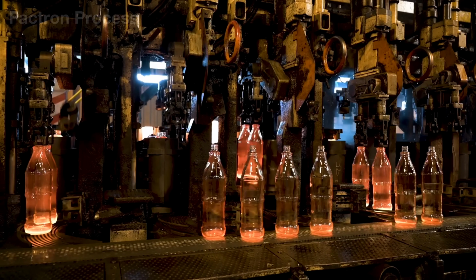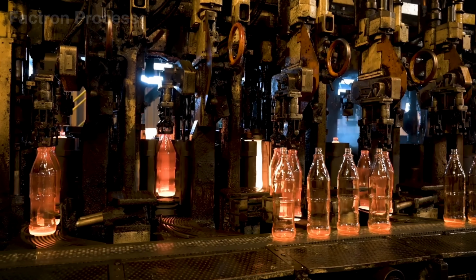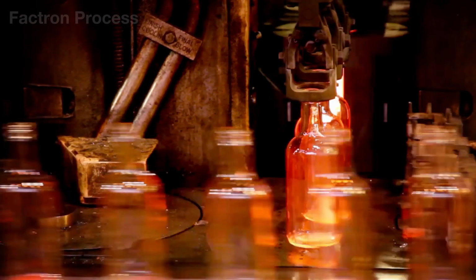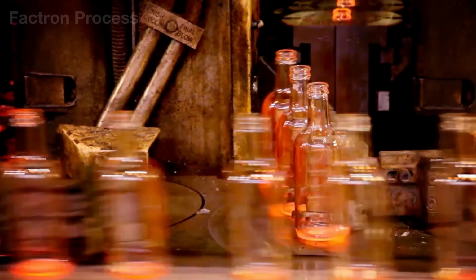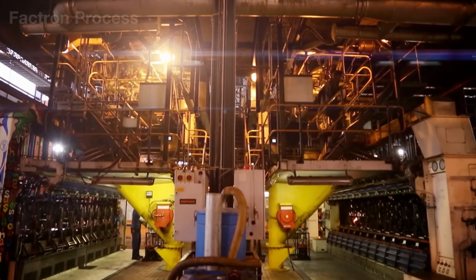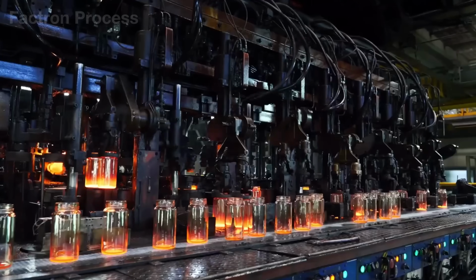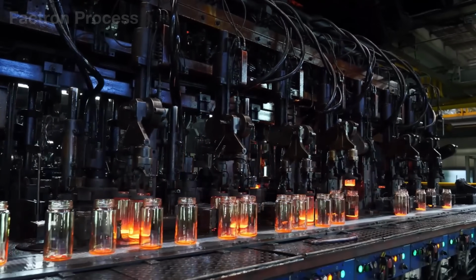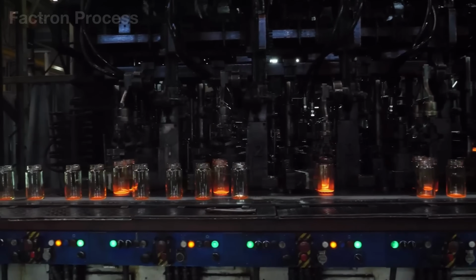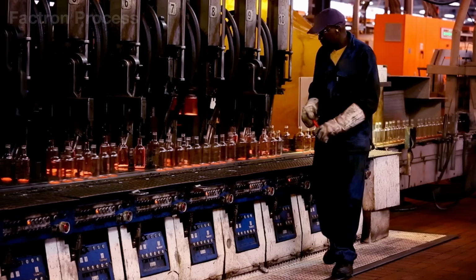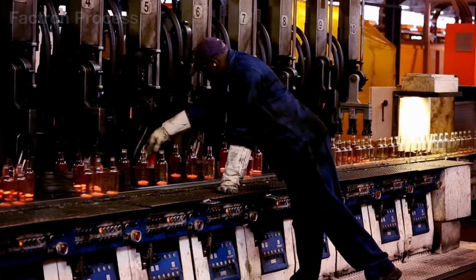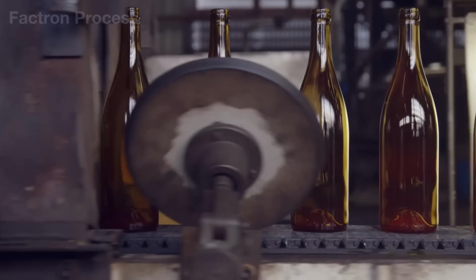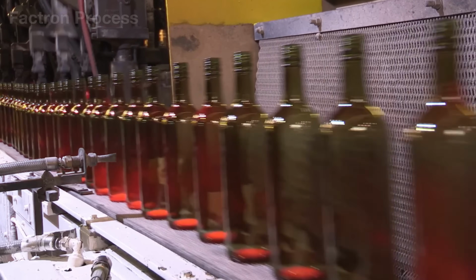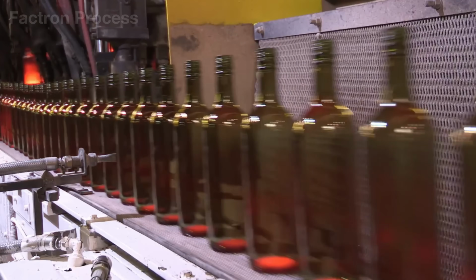On modern production lines, the entire process, from the moment a gob enters the mold to the completion of the bottle's final shape, typically takes only 10 to 15 seconds. During that time, the glass must be distributed evenly throughout the bottle wall. If one area is too thin, the bottle may break during transportation. If it is too thick, manufacturers can waste millions of pounds of raw material each year. That is why modern forming systems continuously monitor air pressure, temperature, and blowing time to ensure that every bottle leaving the mold is nearly identical to the next.